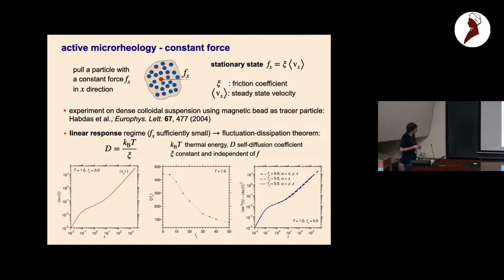Now, in the linear response regime, we have an exact result which relates this friction coefficient with the self-diffusion coefficient in equilibrium. This is an example of a fluctuation dissipation theorem. So here, the self-diffusion coefficient is given by kBT divided by xi.